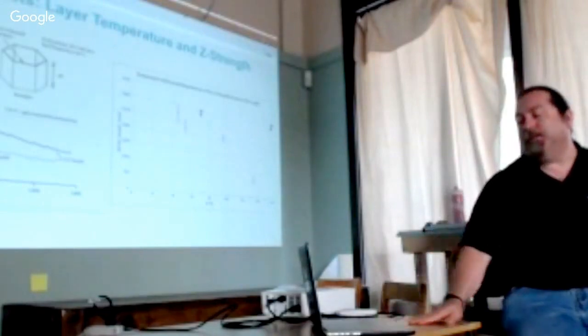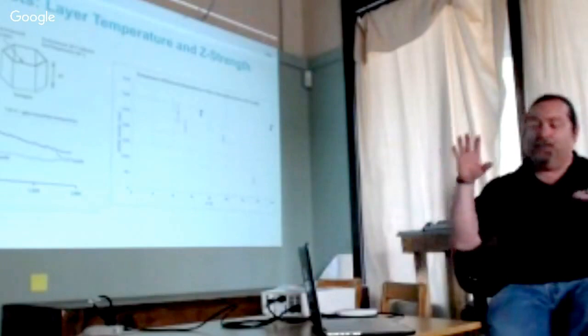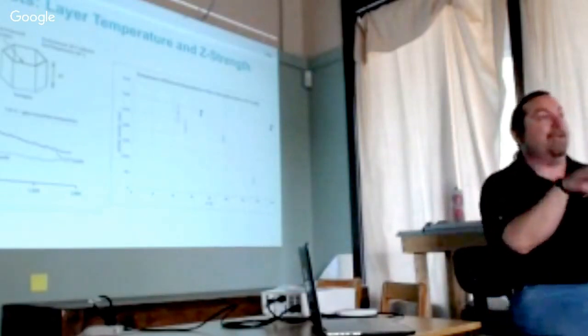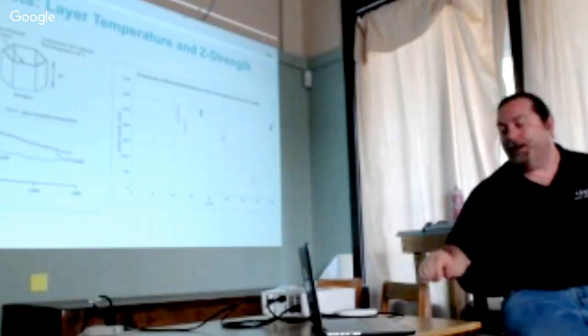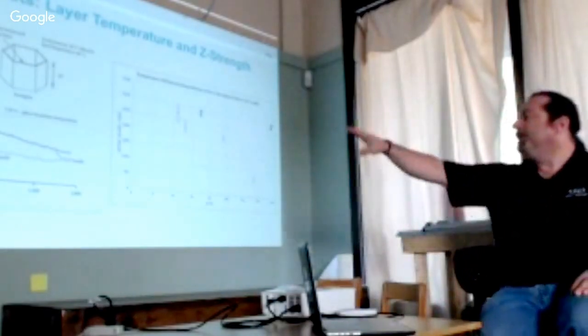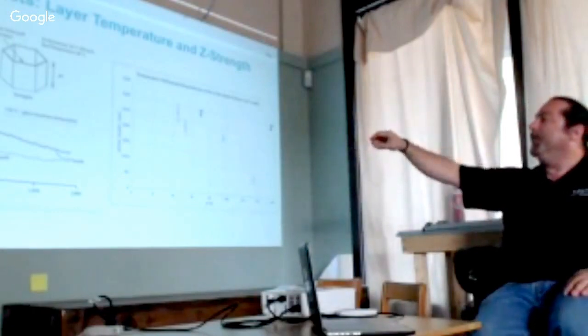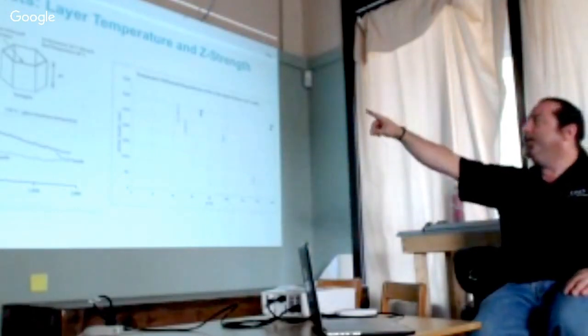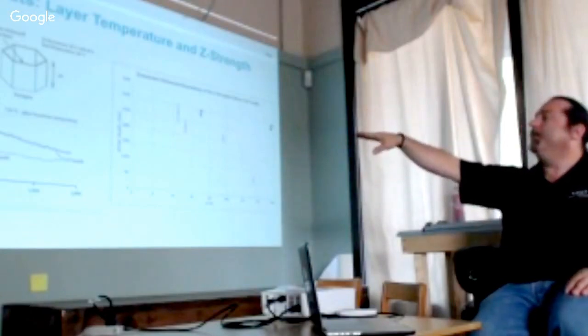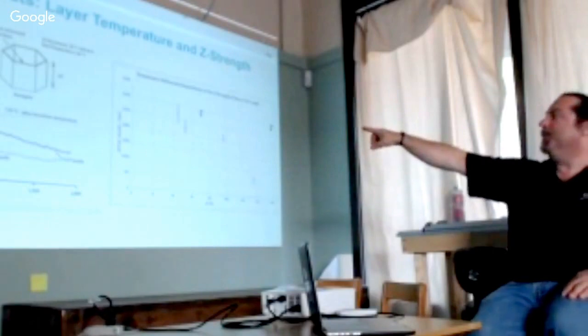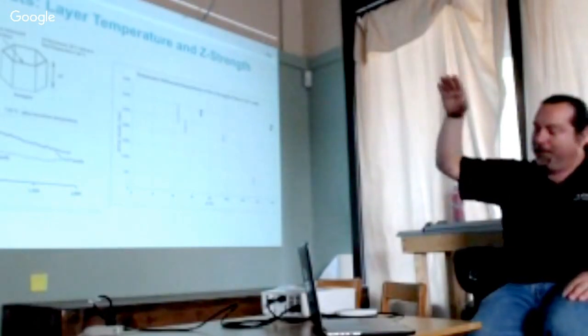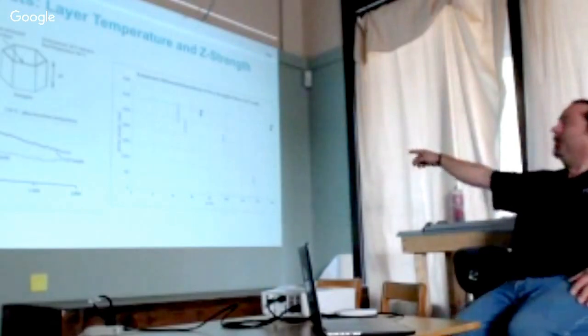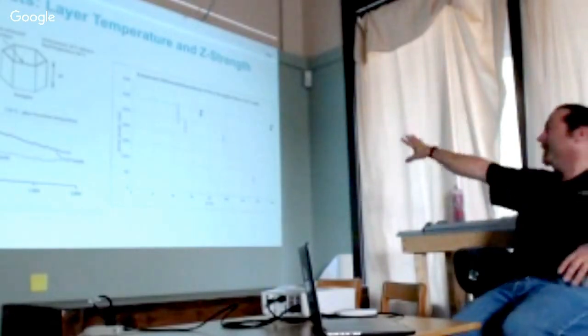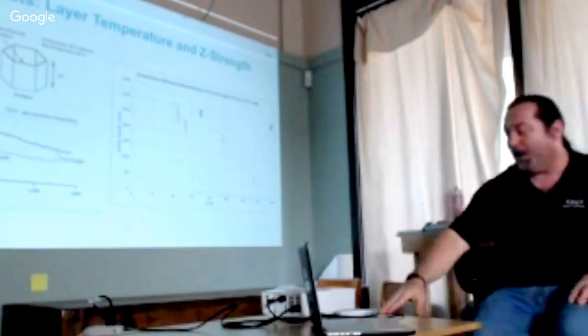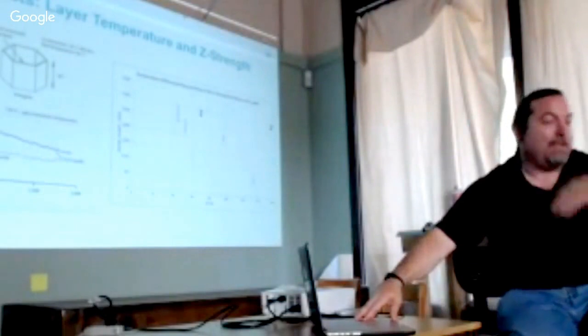So I mentioned the time between layers, and this was when you're using the IR camera to measure the surface temperature during printing. It shows surface temperature as a function of time. So the parts are cooling, but it varies. One's a single bead wall versus a double bead wall. So it gives you basically more time before that layer drops below the glass transition temperature of the polymer. And once it drops below the glass transition temperature, that's where we see the strength really drop off. So that's the second plot, which shows how that Z strength drops off after the temperature drops below the glass transition.